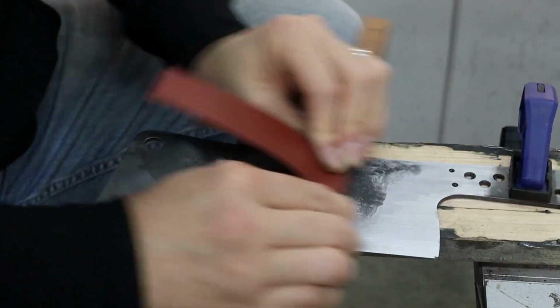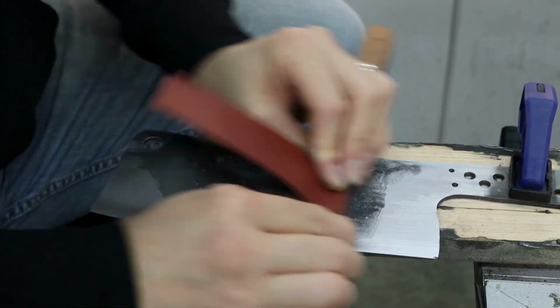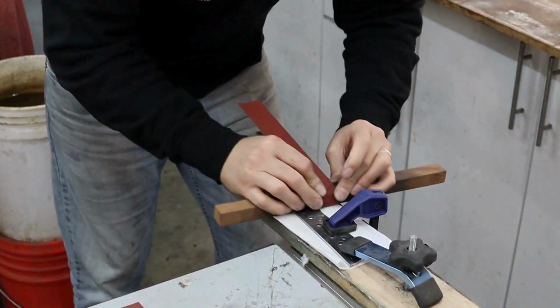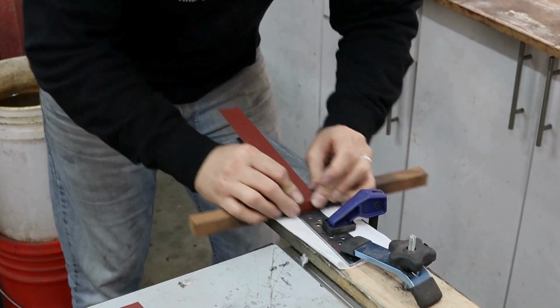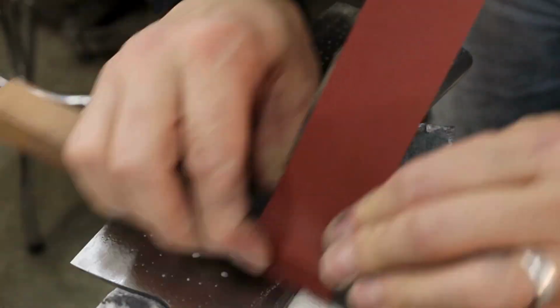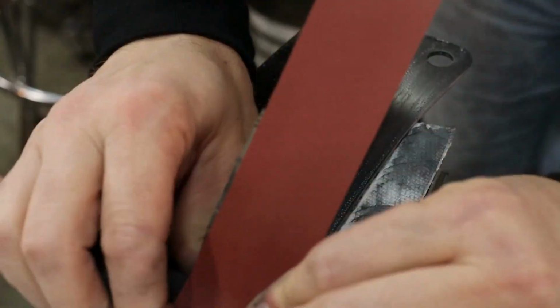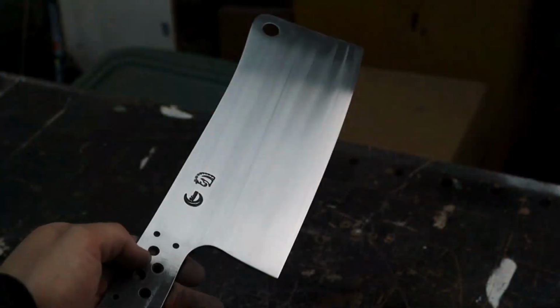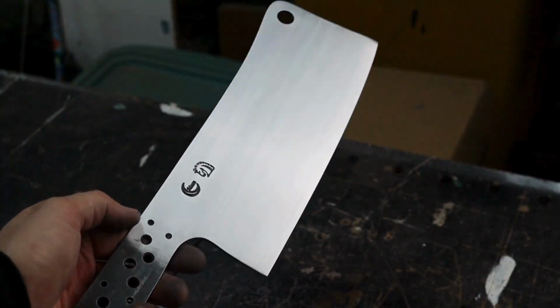At 400 grit, I switched from a steel backer to a cherry wood sanding stick. This has a slight amount of give and blends the finish better across the contours of the blade. I took the finish up to 600 grit and ended with long continuous passes to make sure I don't leave any J-hooks behind. Here's a look at the 600 grit finish.